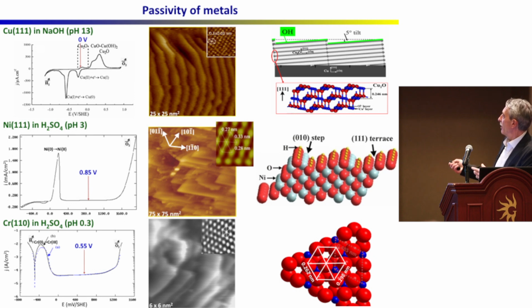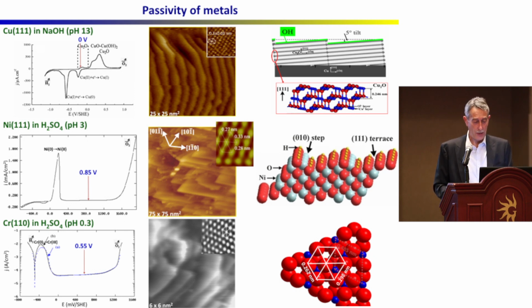And so what we did, and I'm not going to show the data, but Jerry mentioned this work, is that we did some DFT calculations to look at where these chlorides would react. And actually, not surprisingly, what the DFT was showing was that the chloride would replace the OH at the step edges, so that the initiation of the localized corrosion would be the replacement of these hydroxyl groups which are decorating the step edges. And that would be the initial stage of localized corrosion.